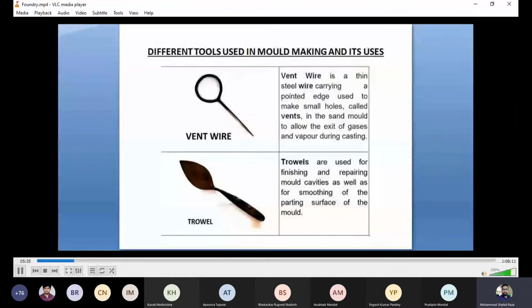These holes are made to puncture only the backing sand layer. We can't afford to puncture the facing sand, otherwise the mold cavity will have a direct connection with the outside atmospheric air. So when we pour the molten metal, it may leak out through the vent hole. And hence, care has to be adopted when making the vent holes. The depth of the vent holes is only to puncture the backing sand layer.